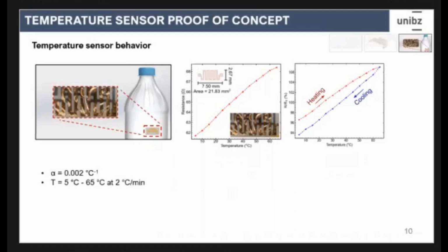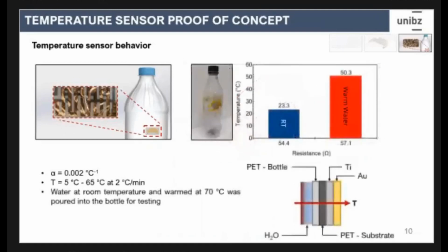Finally, we tested it in a real-life application, where we put it in a bottle. We pour water at 70 degrees to see how accurately we can measure the temperature. But remember that we are filling the bottle with water, so there's conduction between the water, the first PET layer from the bottle, the second PET layer from the sensor itself, then the titanium layer and the gold layer. So in the end, when we pour the 70-degree water inside, we end up reading 50.3 degrees from the sensor itself. Of course, it was just a quick experiment. It can be fully optimized and get more accurate results with further research.